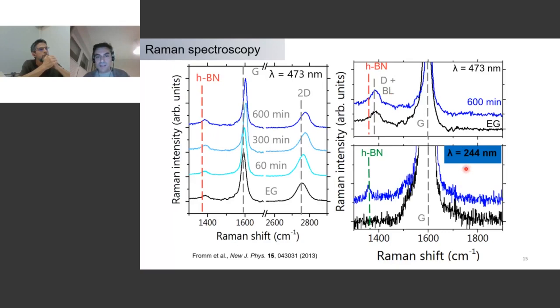But if we move to excitation with an ultraviolet laser wavelength, then what happens is that this D peak and the buffer layer signal are strongly quenched, because the D peak is actually energy dispersive, so it shifts in energy and also decreases in intensity. And the good news is that you are then going close to the resonance cross section in hBN because of the high band gap, so you are able to excite hBN. But it's a very thin layer that we are forming, and that's why you see a very small contribution of hBN. At least we know this is an indication by Raman that we form hBN.